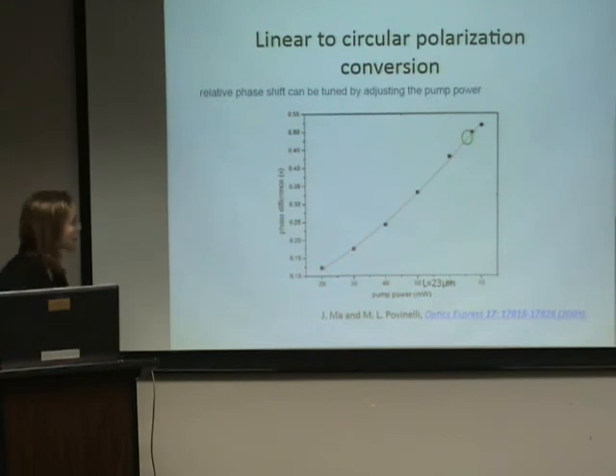The conclusion that we found in this work is that if you have one of these structures for very reasonable powers and realistic geometry, you can convert linearly polarized light to circularly polarized light using this effect, and you can do it in a tunable way. So as you adjust the pump power, you adjust the phase shift, and you can go from linear to circular.